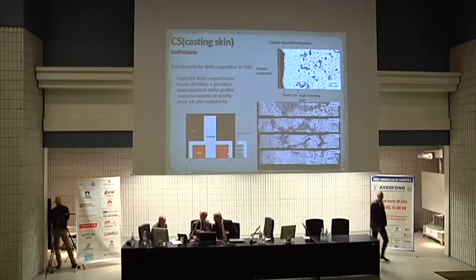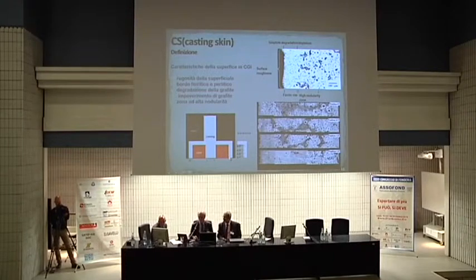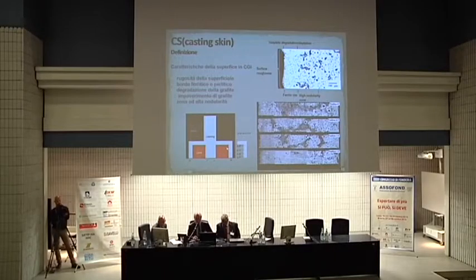And this is an example from a casting. Here is a core. Here is a casting. So you can see here that depending on the height in the mold, so these are 4 different micrographs at 4 different heights, for the same material and same molding materials, you can have quite a significant change in the thickness of the skin.